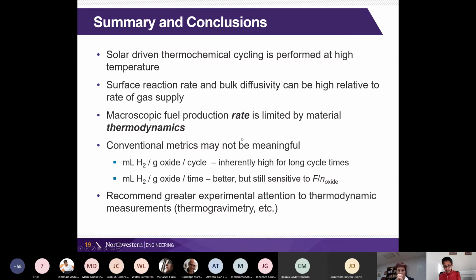Also, an important thing is that these conventional metrics that we use, like milliliters of hydrogen per gram of oxide per cycle, is not very meaningful, because, of course, we can do a very long cycle and get more fuel. If we do this looking at it per unit time, taking into account the cycle length, that's better, but then that becomes sensitive to the flow rate relative to the oxide mass. So we don't typically report these numbers, but I can show you that we can manipulate this parameter at will simply by changing the flow rate of gas and the moles of oxide that we put into our reactor. So we need to be very careful about that. So my personal view is that we pay greater experimental attention to the thermodynamic measurements, so thermogravimetric measurements and other ways of getting those thermodynamic properties.